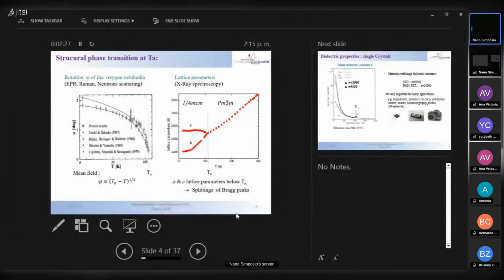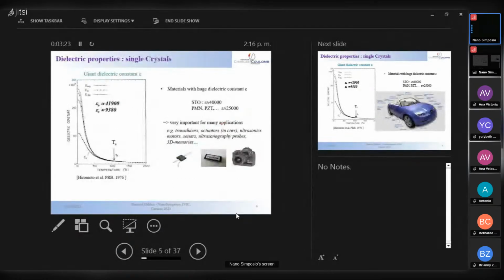And so you can measure these two quantities, for the angle, the rotation angle of the octahedra here. You have the zero value above 105K, and below you have the growth of this angle. You can measure this angle by many techniques: EPR, Raman, neutron scattering. There are many ways to measure this angle. And same for the lattice parameters. You are cubic at high temperature, so there is just one lattice parameter A for the cube. And then below 105K, the C-axis develops here, and you have a splitting of this A lattice parameter. So those are the two structural things which develop below the transition at 105K, the C-axis and an angle.